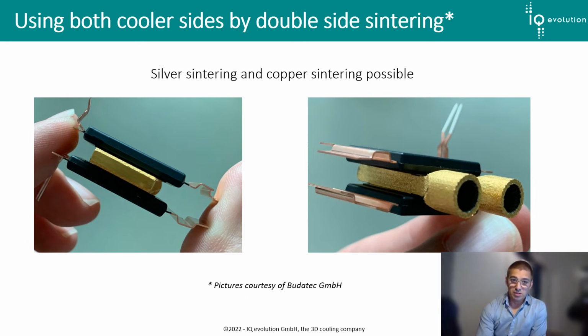One example of this is being shown here. You see this package is being used by Tesla and has been silver and copper sintered to an IQ Twin with a nickel and gold metallization. The pressure used was about 25 megapascal, and one reason we will ask you after the dimensions of the coolers and die location is that we want to make sure that the coolers are built for pressure sintering.